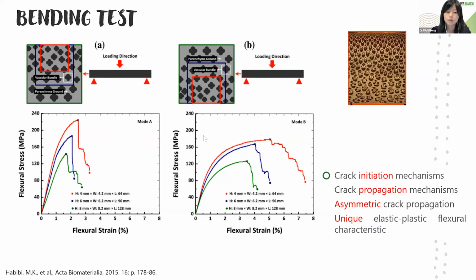We can see that the stress strain curve in the first stage is not linear. It's a nonlinear deformation, especially before the fracture point. This is associated with the squeezing of the parenchyma cells, because previously we already know the parenchyma cells are more like a capsule shape. So this area contains more space, which gives more space for compression. Compared to model A, it does not have this phenomenon. Another thing is that it has more serrations here. This is also because there are more delaminations across in model B.